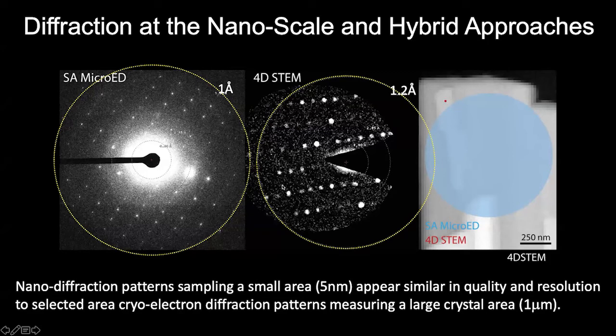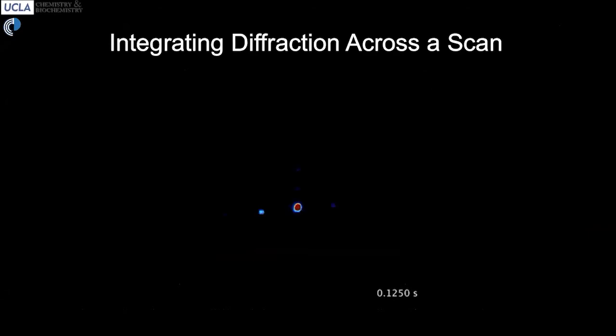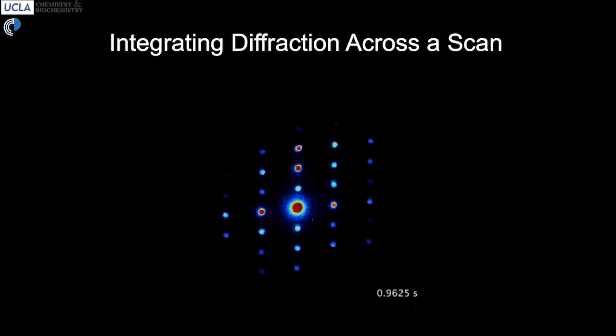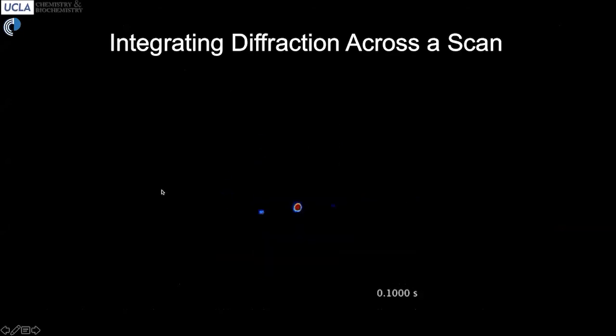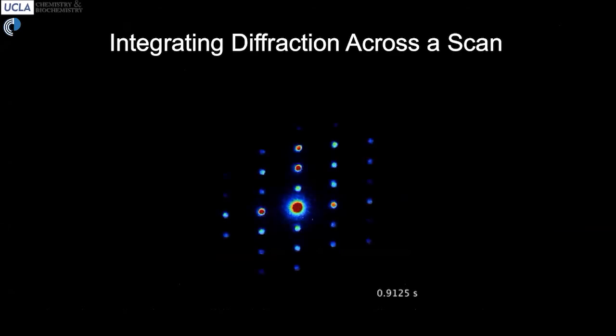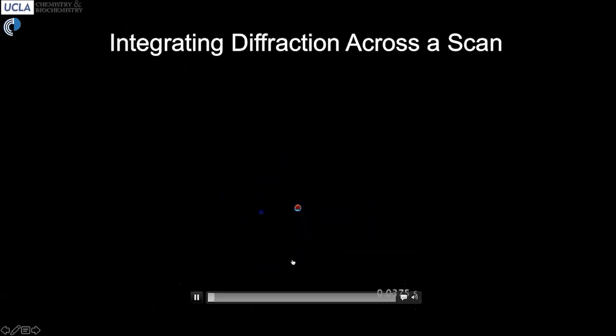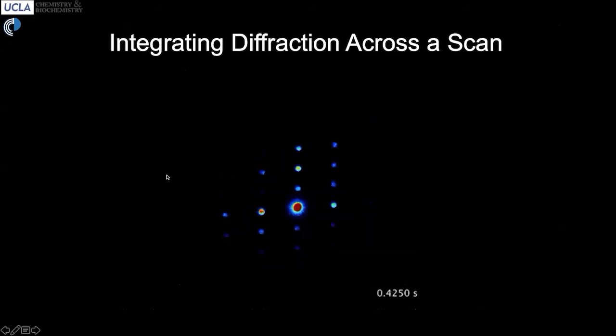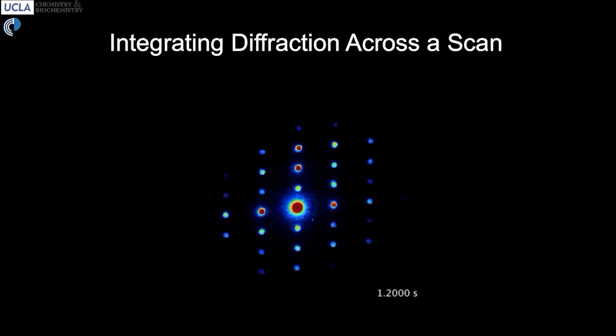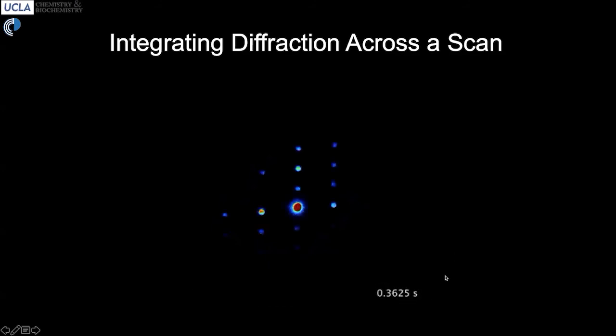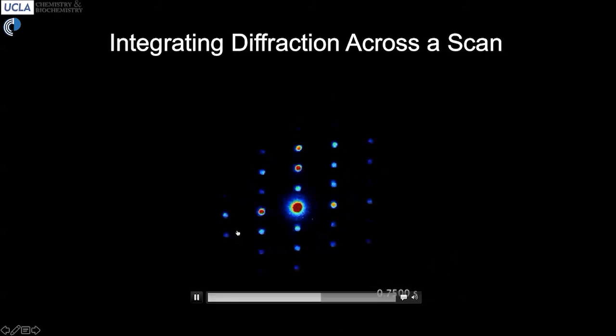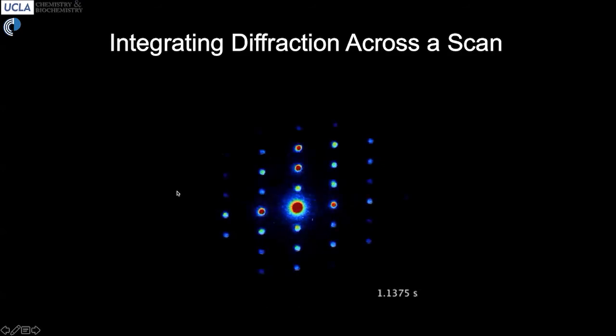And so what we've done along with our partners at LBL is to try and raster scan that beam across a sample and either integrate the signal as you see on the screen here. So this is just integrated signal over relatively large area. As that beam is scanning, we're just summing up all of the information onto one single diffraction pattern. And this would be something equivalent to accumulating a single diffraction pattern using selected area diffraction. And you can see how long it takes to integrate here. This is about a second of information that is being recorded on this single image.